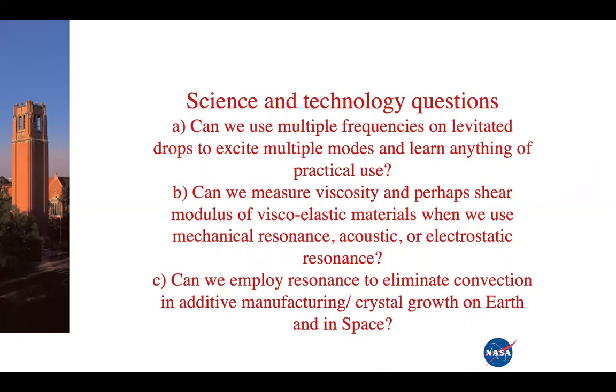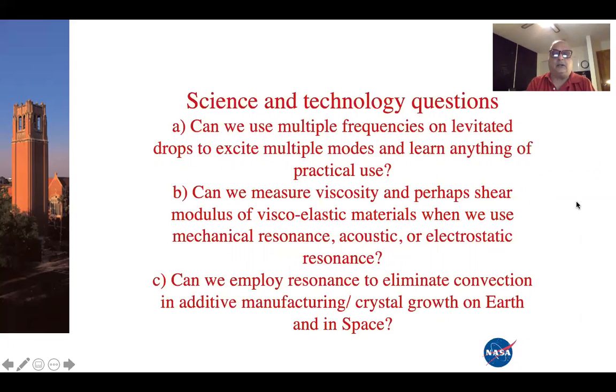Can we employ resonance to eliminate convection? Now, this is a new idea, because resonance not only makes a stable system unstable, but it will make an erstwhile unstable system, say a thermoconvective system, stable. So if you take a convective system and you try to shake it, you will actually begin to stabilize it. In other words, you have a system which is causing convection on Earth due to thermal gradients, due to buoyancy, or in space due to Marangoni convection. Perhaps by imposing acoustic signals or mechanical resonance or even electrostatic resonance, we can quench that convection.